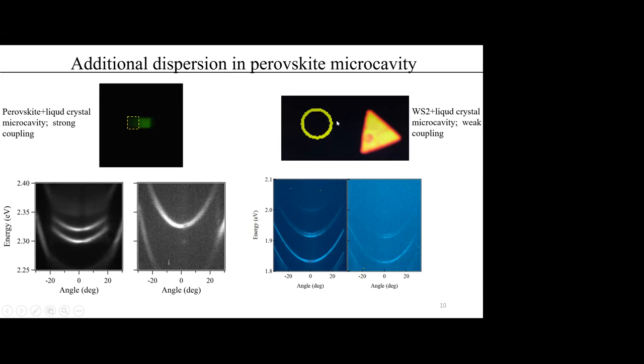the red graph. Here we fabricate a new liquid crystal microcavity where a WS2 monolayer is inserted in the cavity layer. The structure of this new microcavity is the same as the perovskite microcavity. In this new microcavity, only weak coupling between the excitons of the monolayer and the cavity modes is observed. In this case, we can see that the dispersion of the monolayer area and the other area is the same.